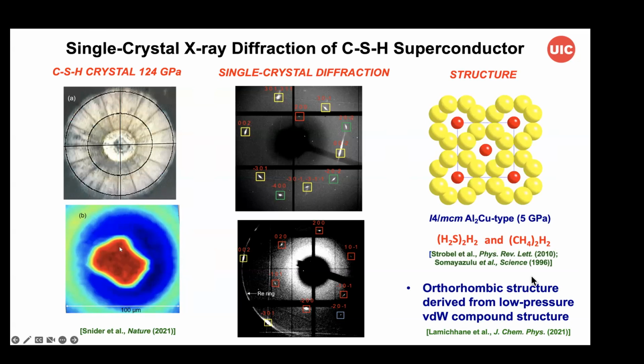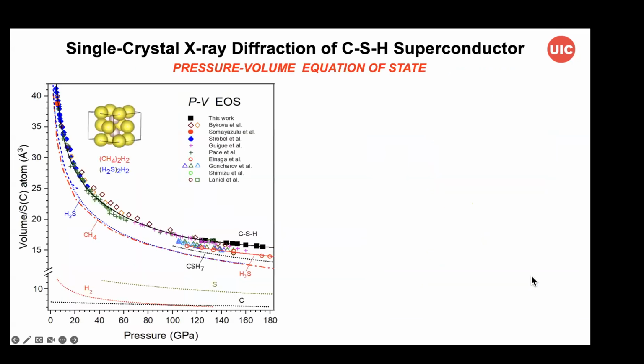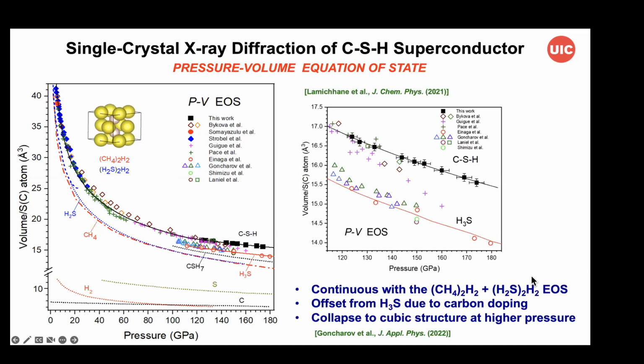It goes into an orthorhombic structure, and in the equation of state measurements shown here, we see this continuity with the low pressure EOSs. We also show the various PV curves for the components. So you can understand the compression in terms of the compression of the molecular and atomic components in the system. And here's a blow-up of the higher pressure range showing H3S as well as CSH, and this offset is due to the presence in some fashion of carbon in the system.